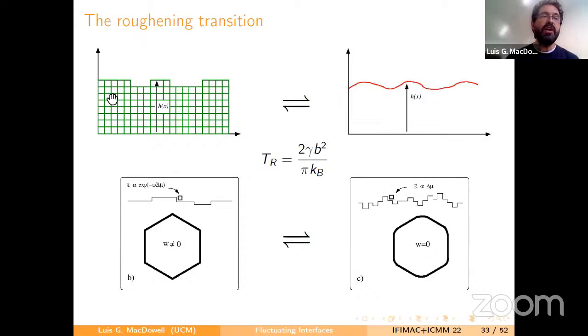Okay, as long as you are here in the faceted region of the interface, then growth is very slow. It occurs by two-dimensional nucleation, and it's an activated process. So it's very slow growth. However, if you go across the roughening transition, then it's like having many kinks in your interface. It's like a continuous interface. So whatever atom falls there is going to stick. And then you have very fast, not activated growth. It's linear in the supersaturation. Okay, so it means that the roughening transition has a great impact on how crystals grow.